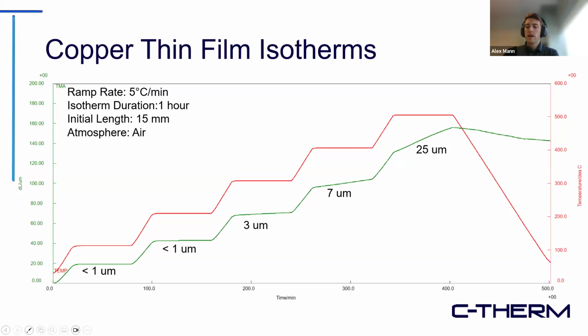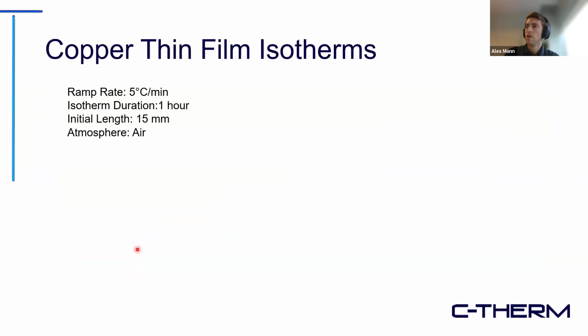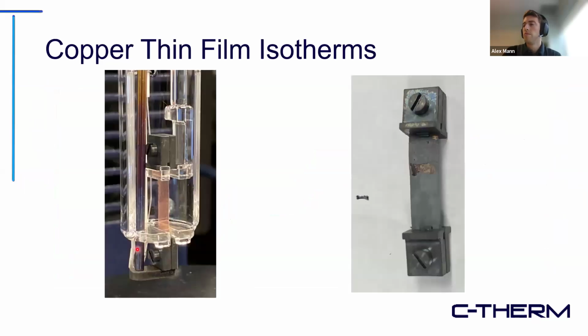This test was designed to emulate how copper will behave whenever electronics overheat. The takeaway is that if it overheats to 100, 200 degrees, you can still kind of salvage it. But once it hits 300, 400, 500, you get irreversible damage happening to the copper thin film. So here is the before and after picture. I was initially planning on labeling them, but I think it's clear that copper film isn't supposed to look like this.